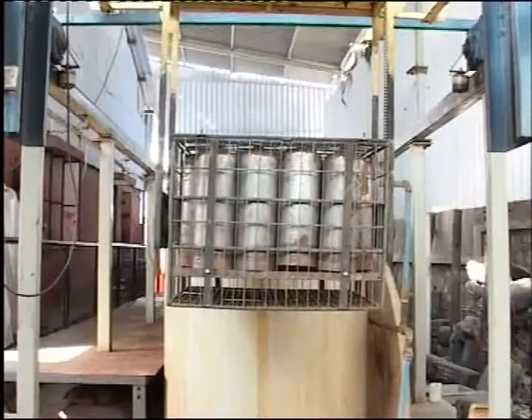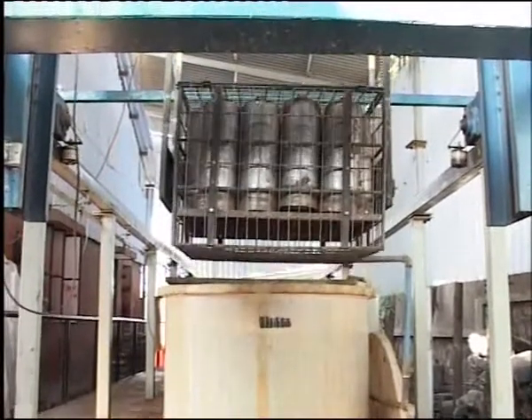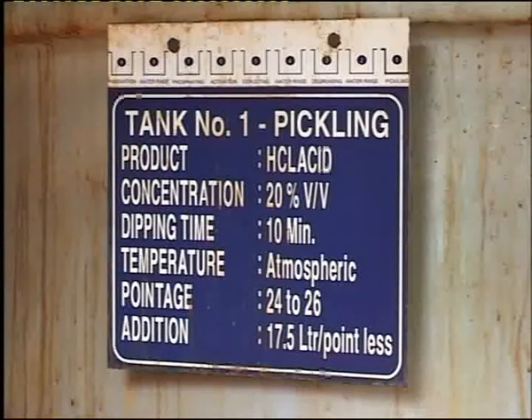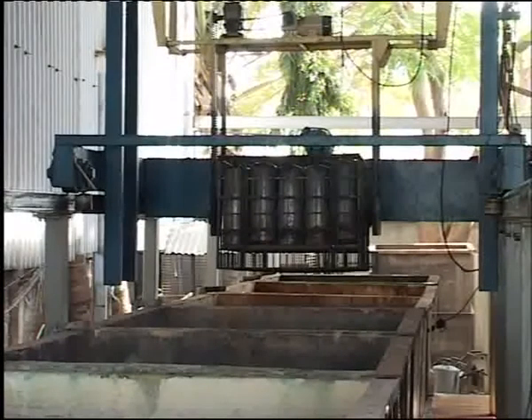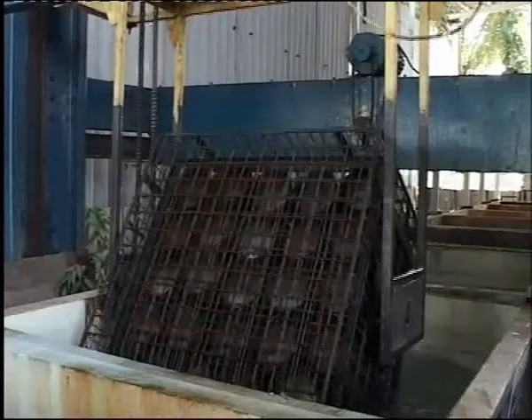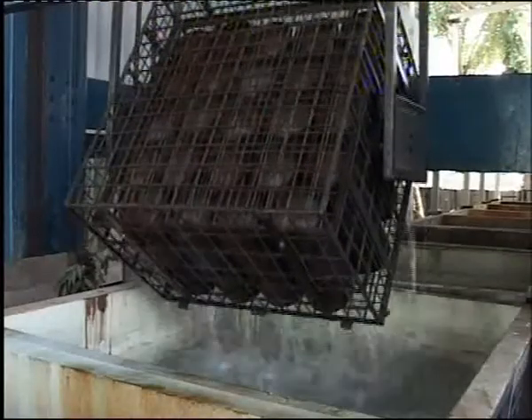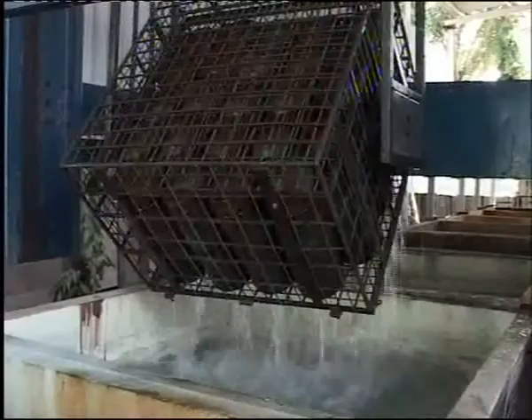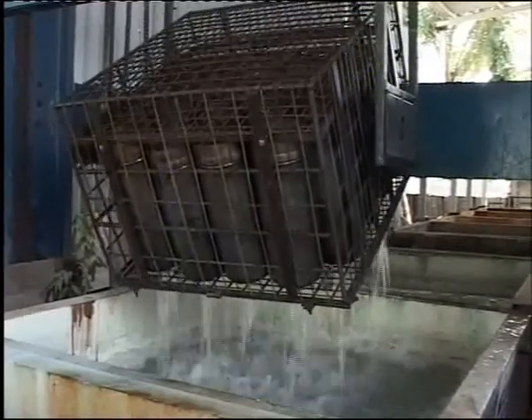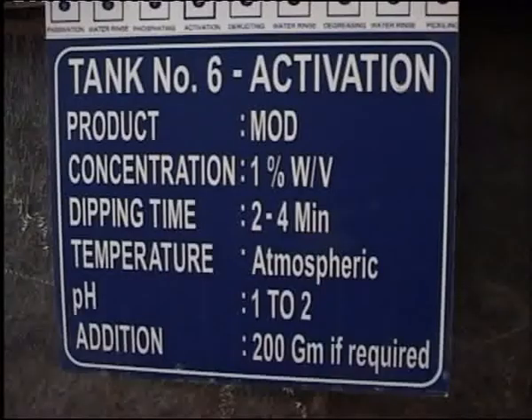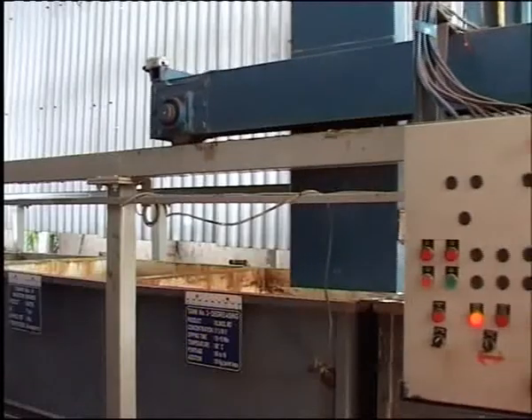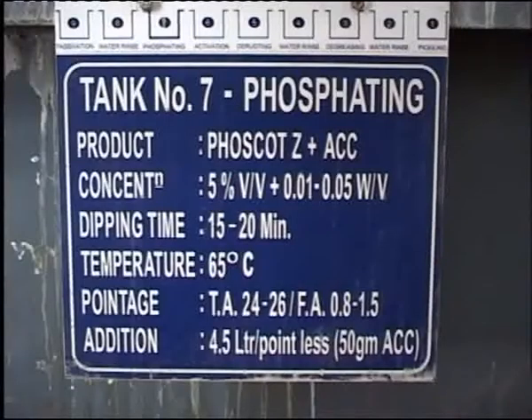Empty cylinders are loaded into baskets and passed through one by one different processes like pickling, where iron oxides are removed, degreasing, where grease oil is removed, carbonaceous deposits are removed from the ferrous surface. Derusting removes dust, oxides, smut and scale from the surface. The activation tank makes material active for the phosphate treatment. At the phosphate tank, the layer of phosphate coating is produced to serve as an excellent base of powder coating.